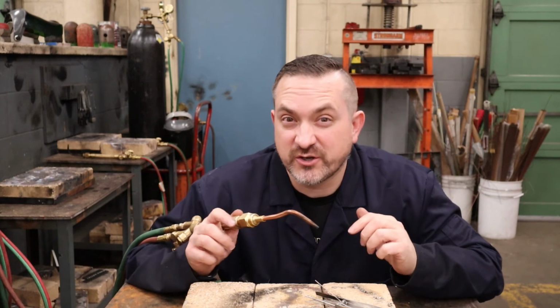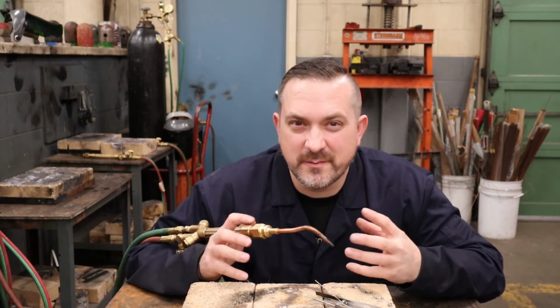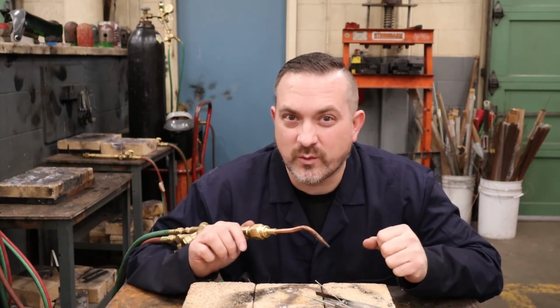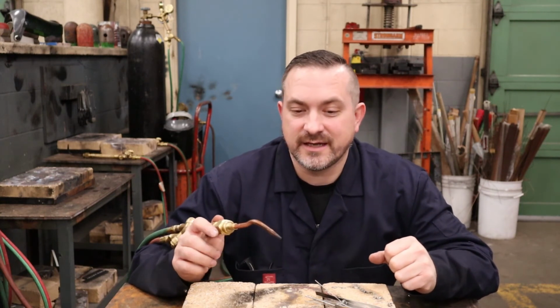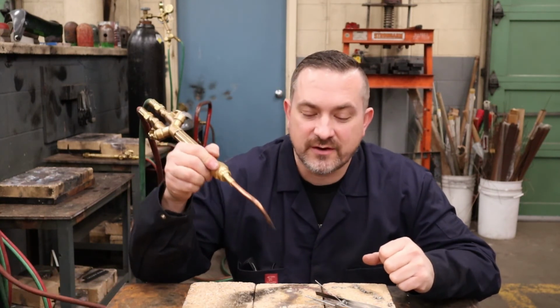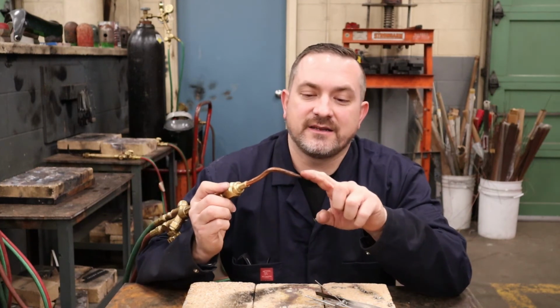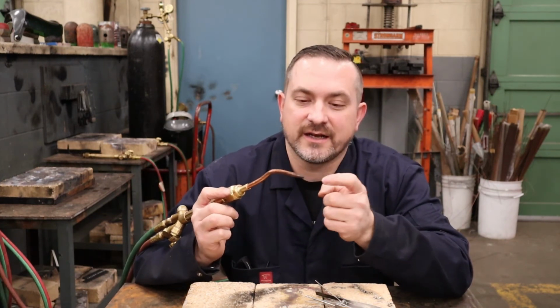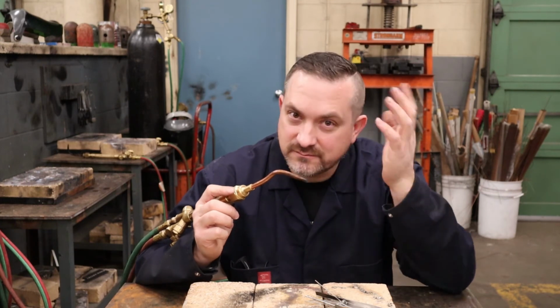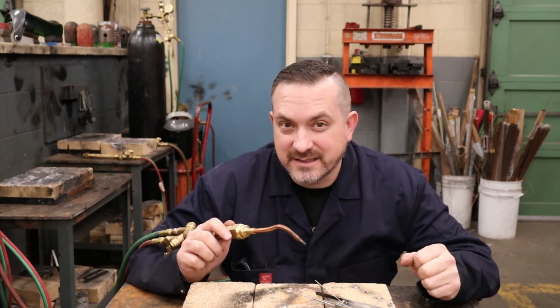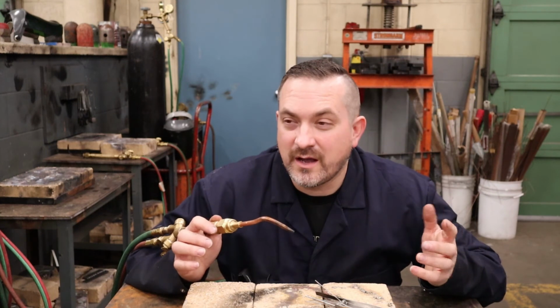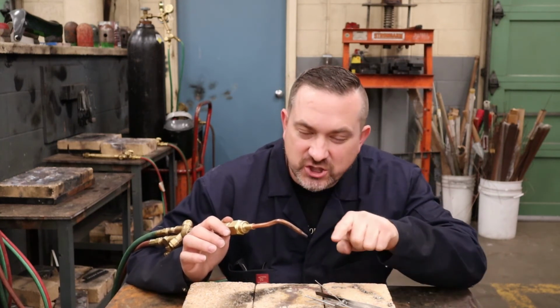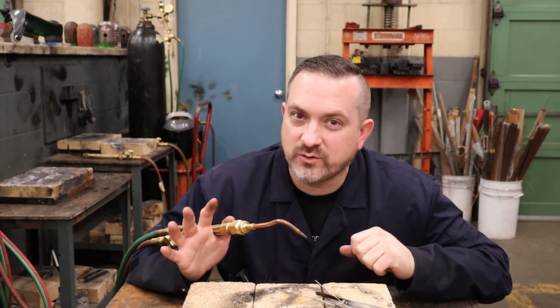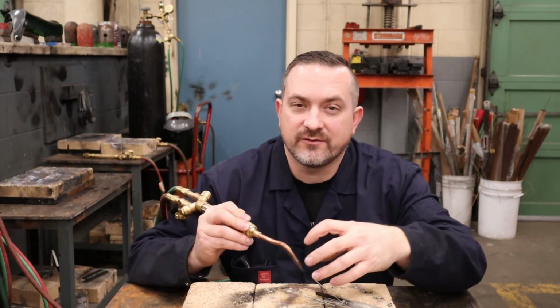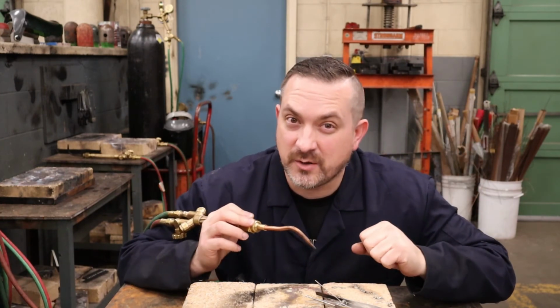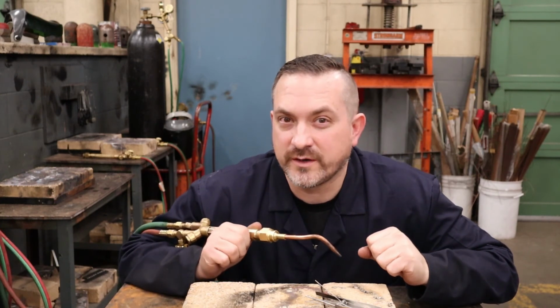Third thing, take a look at your materials. Make sure that there is no debris or mill scale on it that's going to make it pop when you start welding. And fourth, take a look at the distance that your welding tip is from the puddle or the heat, because as the end of this welding tip starts to get hot, you can actually get the gases to explode inside here, hence the pop. And one of the last things is an oxidizing flame. If you hear a really loud sound and you've got a really sharp cone, that's an oxidizing flame, and it's way too hot, and it's going to give off lots of sparks and then eventually pop. So lots of stuff to look for when you're having issues with popping.